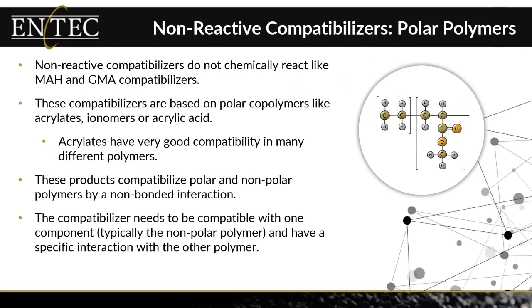And now if we move on to non-reactive compatibilizers, maleic anhydride and glycidyl methacrylate have chemical reactions that occur, so they provide very, very good bonding, very, very good compatibility between your two polymers. The non-reactive ones do not have a chemical reaction. And many of these are based on polar materials like acrylates, ionomers, and acrylic acids. And one comment, the acrylate materials are utilized extensively because they have generally good compatibility in a wide range of polymer systems. So they can work very effectively at compatibilizing polyolefins to a wide range of polar materials.